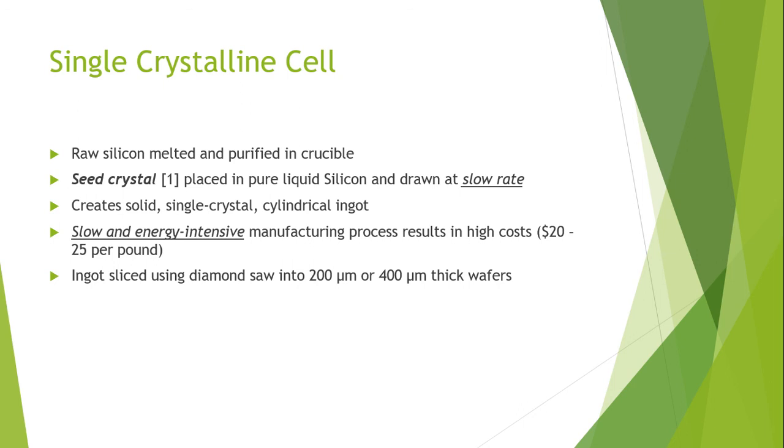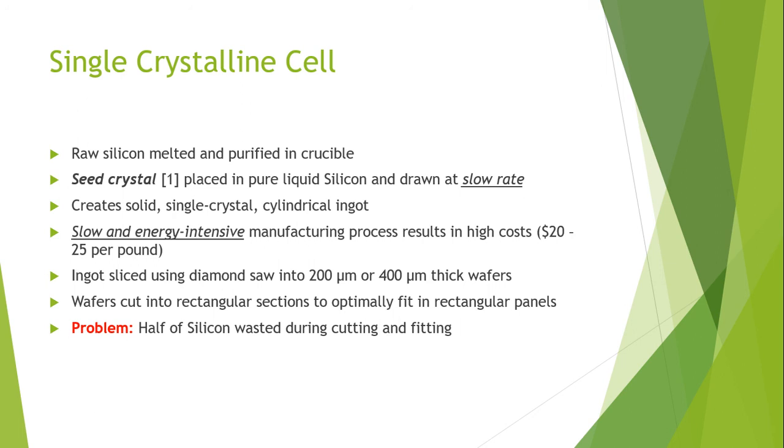The ingot is sliced using a diamond saw into 200 micrometer or 400 micrometer thick wafers. Wafers are cut into rectangular sections to optimally fit in the rectangular panel.